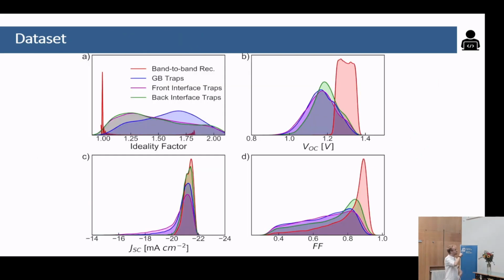So now we generated a data set that kind of looks like this, where I have many different data, and you can see that, for example, you have a very sharp peak for purely band-to-band dominated carriers. Then for the interface recombination, you tend to have somewhat low ideality factor, close to 1, but not really 1. And as you move your recombination more to the bulk of the material, then it can get close to 2. And you also have different distributions for all the different parameters. And basically we use those values as features to try to get to a conclusion.